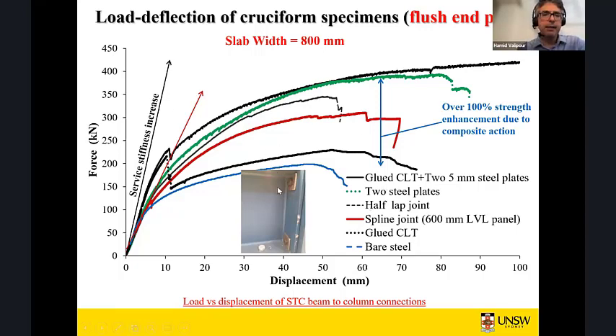Again, the results we get out of the push-down test is load versus midspan deflections. I just want to highlight a few things on this graph. You can see a variety of different connections. You see the glued CLT plus, let's say, steel plates. We got this graph, which goes all the way up, and it shows a peak load close to 400 kilonewton. Just keep that 400 kilonewton number in mind, and then you will see in the next slides, we test steel concrete composite floors with continuous reinforced concrete slab. We got strengths close to 440, which is just 40 kilonewton, or around 10% more than what we get from steel timber composite floors.